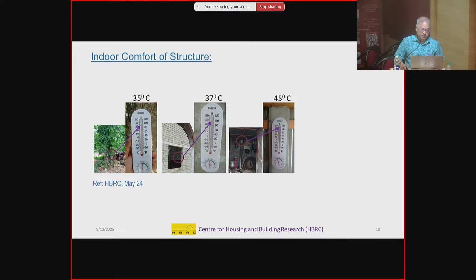Indoor comfort of the structure is my organization HBRC's research work. This is a bamboo bush. In the bamboo bush there was a thermometer, in the ferrocement roof another thermometer, and in the CI sheet roof and wall another thermometer. Below the bamboo bush the temperature is 35, inside the ferrocement roof it is 37. About 75% of houses, especially rural houses in Bangladesh, have CI sheet roofs. That is why it is most important for us to have an alternative to the CI sheet roof. Under the CI sheet roof it is 45, 10 degrees more. So it is very much unhygienic.